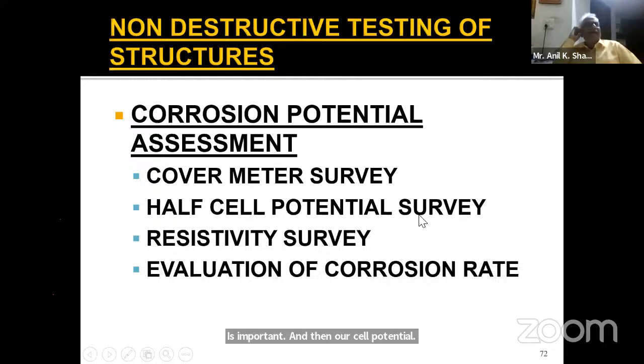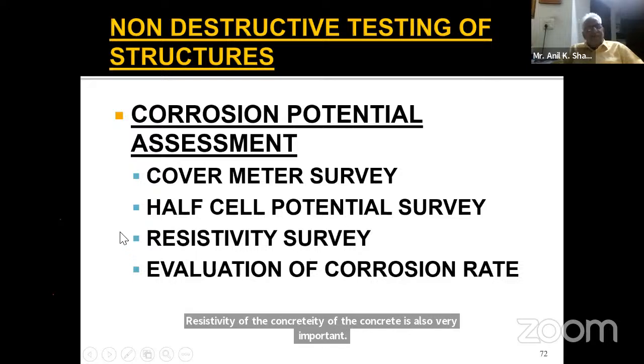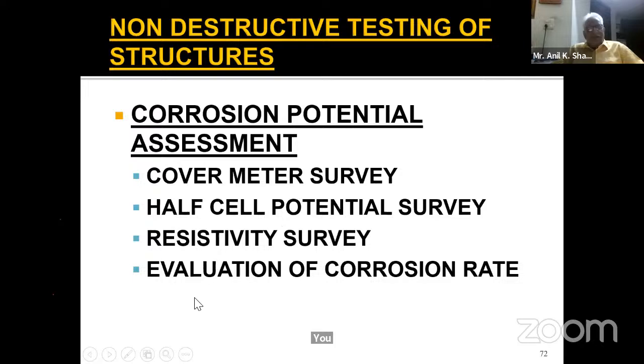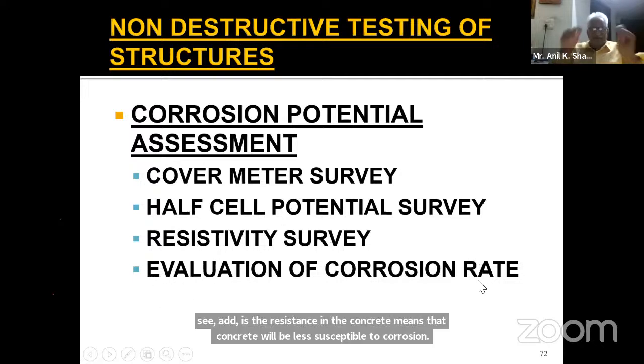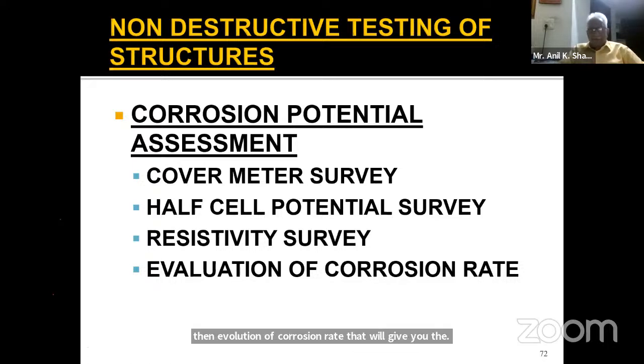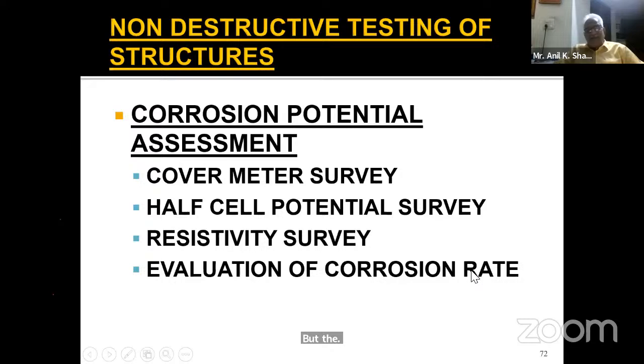You see, corrosion is an electrogalvanic process wherein a corroding reinforcement, the anode, corrodes, and there is a potential difference between the anode and cathode. So half cell potential survey gives you the voltage difference between the reinforcement and the concrete surface. Then resistivity of the concrete. Resistivity of the concrete is also very, very important. You see, the higher the resistance in the concrete, the less susceptible that concrete will be to corrosion. And then evaluation of corrosion rate will give you the remaining lifespan of the building.